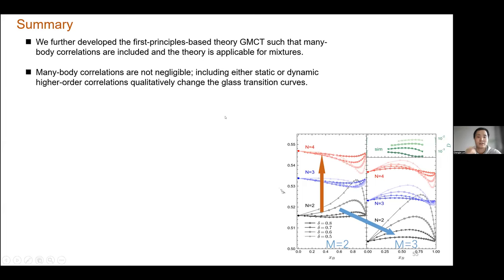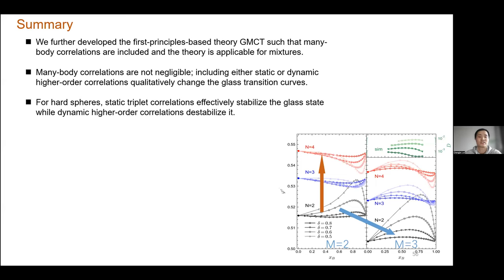And by numerically studying the binary hard-sphere mixture, we demonstrate that many-body correlations are not negligible. Including either static or dynamic higher-order correlations will qualitatively change the glass transition curves. And we find that for hard spheres, static triplet correlations effectively stabilize the glass state, while dynamic higher-order correlations destabilize it. Finally, I have some outlooks.